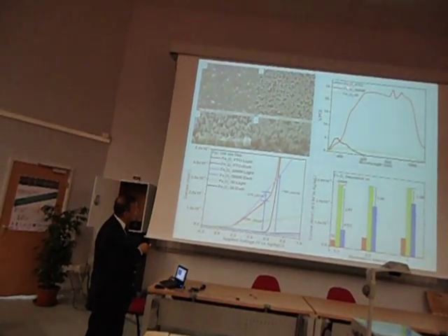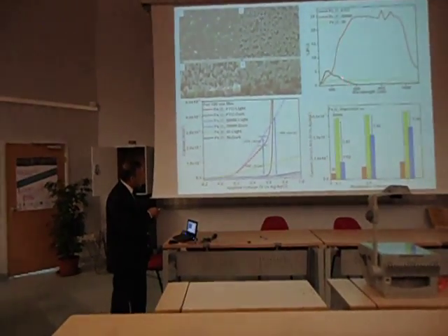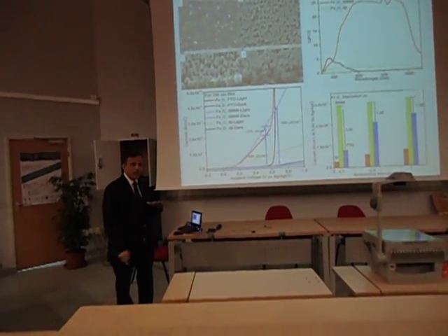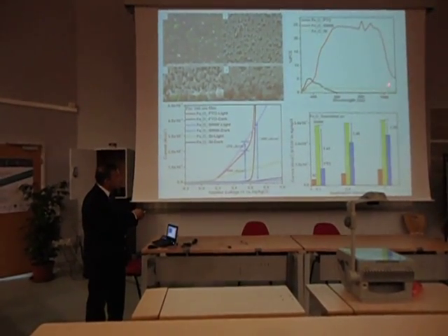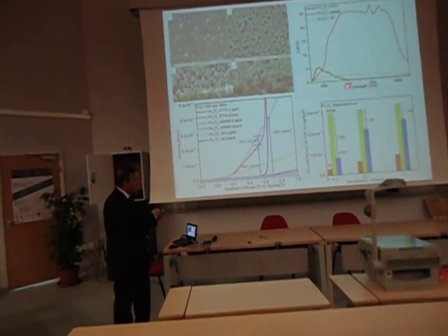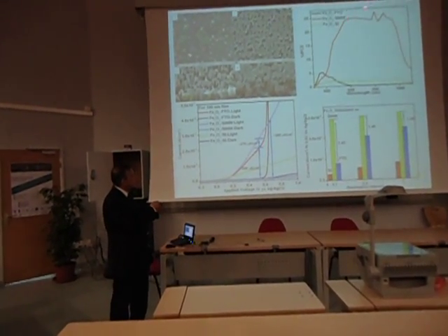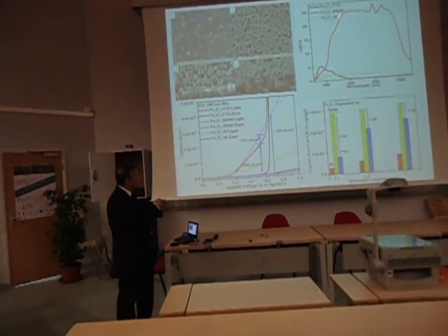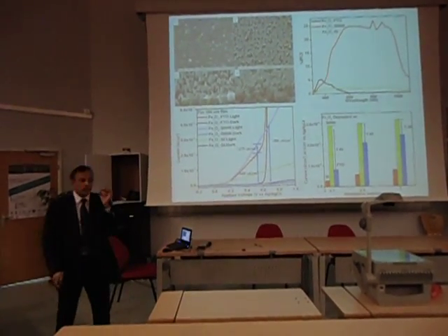Suppose I were to take Fe2O3 and coat it on FTO, okay, I get this particular thing which corresponds to FTO band gap and everything. If I take Fe2O3 and put it on silicon, which is like a single crystal flat silicon, I get this response here. This is actually the band gap of silicon. So it is a response over the whole visible range because silicon is absorbing it, okay. But if you look at the nanowire with Fe2O3, you look at the IPCE here, the internal photon to current conversion efficiency, it is dramatically high like this. So just putting things together in the right configuration makes a big difference.